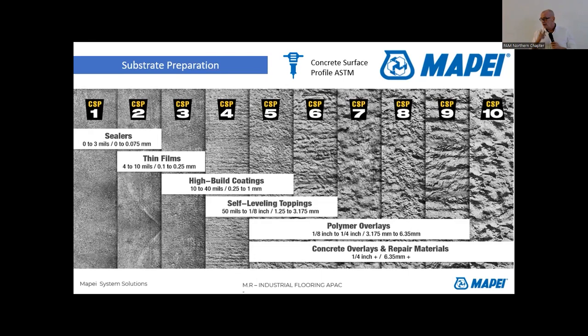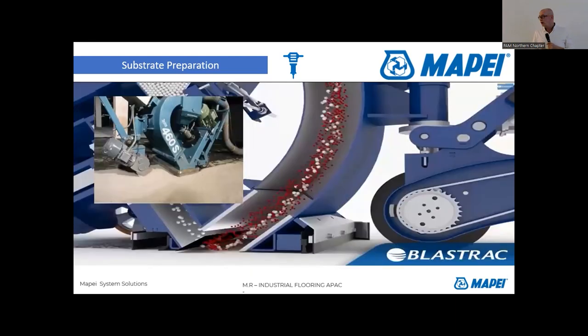Because this is important. If you don't have the roughness, we don't get the interlocking. Penetration is one thing, but we need interlocking. So then we often use a shot blast machine or grinding machines. With the shot blast machine, you remember I said laitance. The aggregates go down, the water comes up during the vibration of the concrete. This machine will remove all this laitance. It's very effective. Depending on the size of the machine, it can make 600, 800 to 1,000 square meters per day. It has a huge vacuum cleaner unit behind it, and it will suck off all the debris as well as the steel bullets shooting on the floor. They get separated once they go into the machine. It's a separation procedure. So this machine can do this.